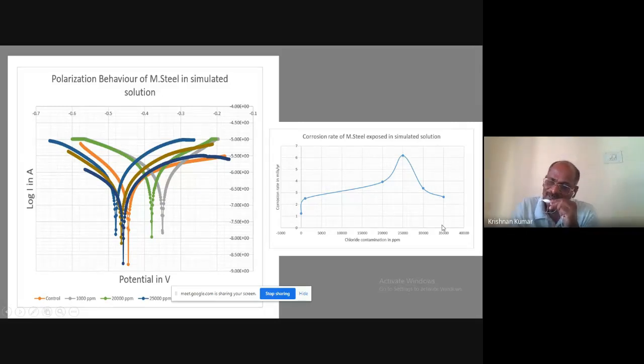What is the reason? When the chloride is sufficient, at 25,000 ppm, it creates the maximum critical level of corrosion, and it forms corrosion product over the surface, so further corrosion is reduced. Further chloride cannot enter there because it is already occupied by the 25,000 ppm in the reaction. So the balance, whatever is available, does not have any effect.